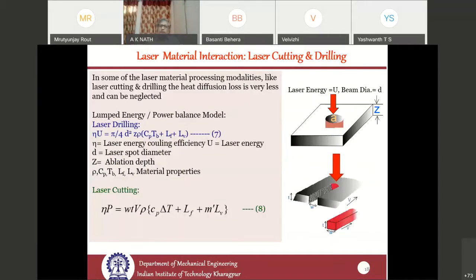However, when we consider normal laser cutting, drilling, etc., where the process is reasonably fast, not like femtosecond laser, but still fast, where heat diffusion losses are very small and can be neglected, one can use the lumped energy or power balance equations given here. This is the energy absorbed, and this is the amount of material which is going to get evaporated through vaporization. So this is the basic energy balance equation.